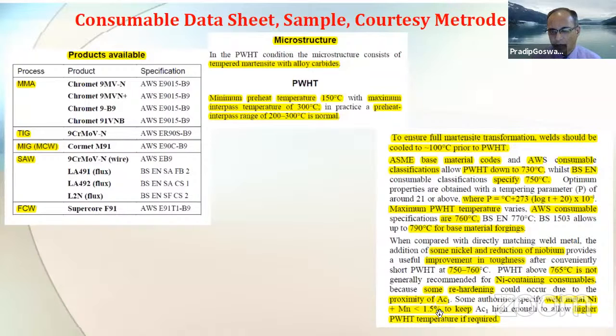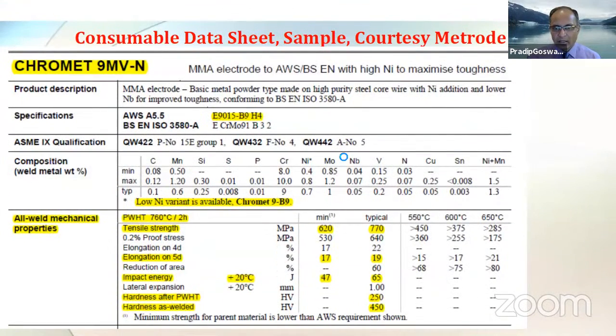As you know, this 1.2 or 1% nickel plus manganese content is very recent, around 2019. So many of the welding consumable manufacturers still have product catalogs that reflect the maximum 1.5% for nickel plus manganese. But leaving that aside, if you consider the post-weld heat treatment and various other properties, they almost remain the same. And this is another quick snapshot on these welding consumables.